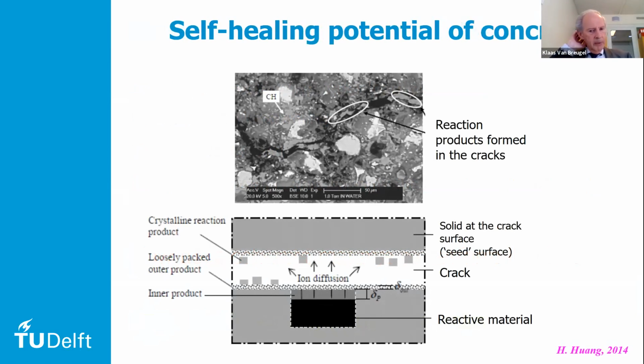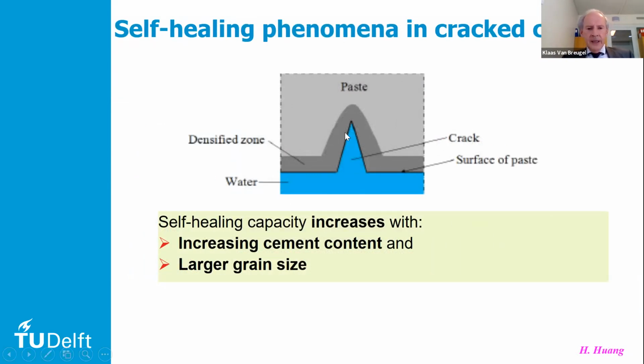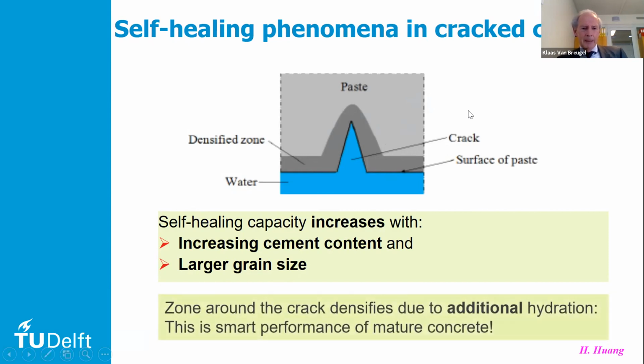The self-healing has been studied by one of our PhD students, Guang, and he has been looking in detail at what is happening in a crack, and he modeled the self-healing that was supposed to occur in a crack. And an interesting thing in his research was that adjacent to a crack, he found that the cement paste was actually densifying due to additional hydration, a degree of hydration that was higher than in the bulk cement paste, a little bit farther away from the crack surface.